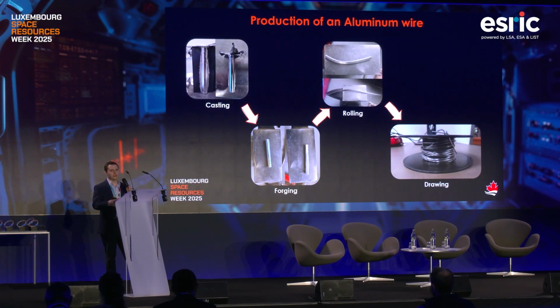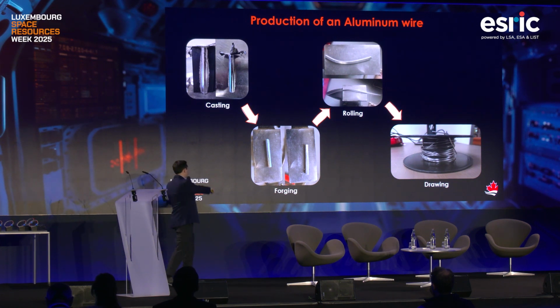Once we got aluminum, we worked on the manufacturing part. What we had to do was to remelt that aluminum and then try to produce something useful with that aluminum. So in this case, first we remelted the aluminum, and then we fluxed it to remove some impurities. And then we went through the casting process. We poured that into a mold, and we made a cylinder. We removed any excess material. And after that, we worked on forging it.